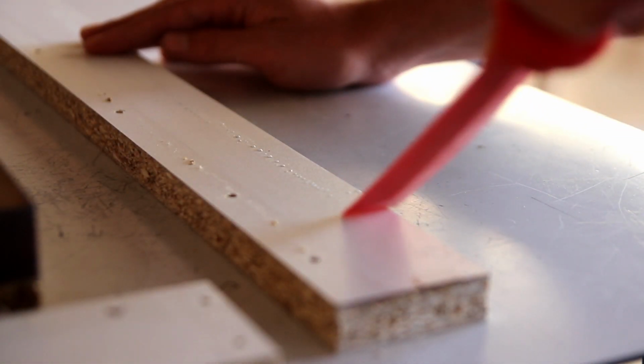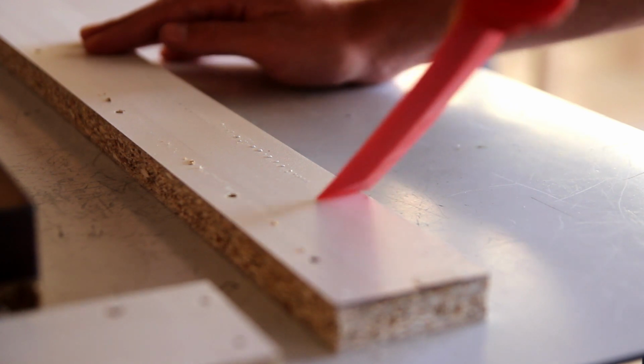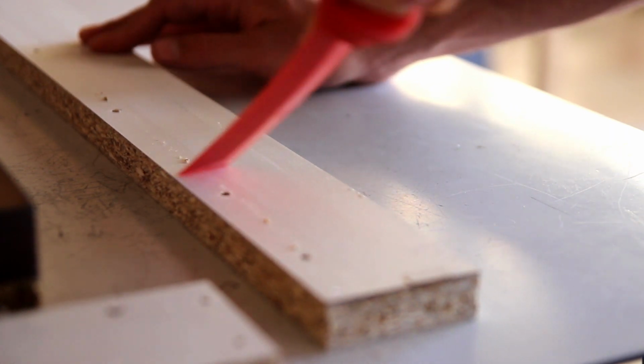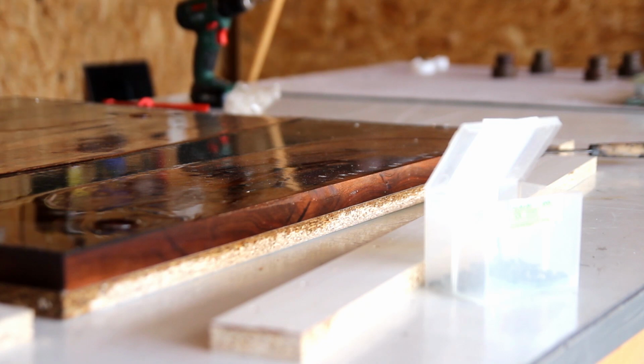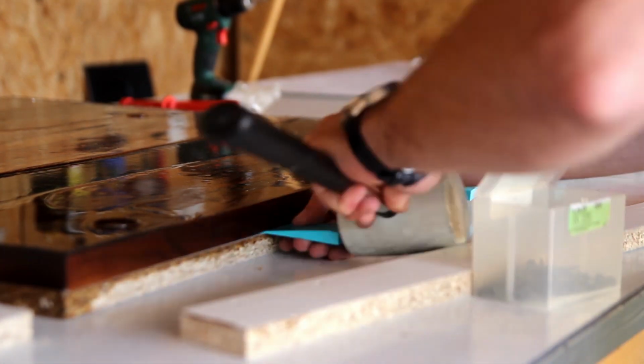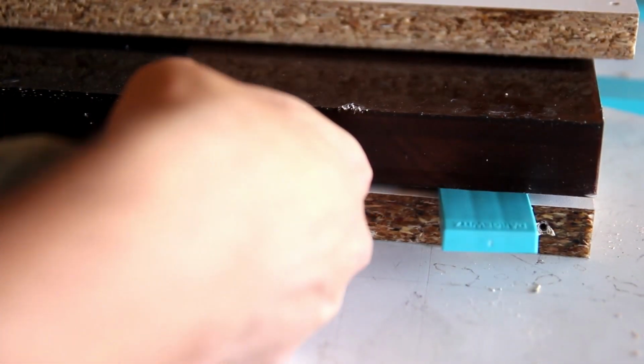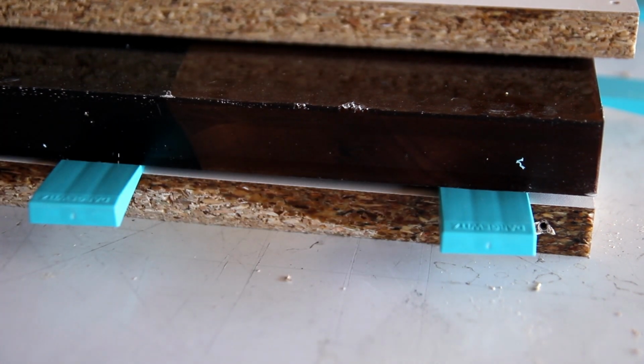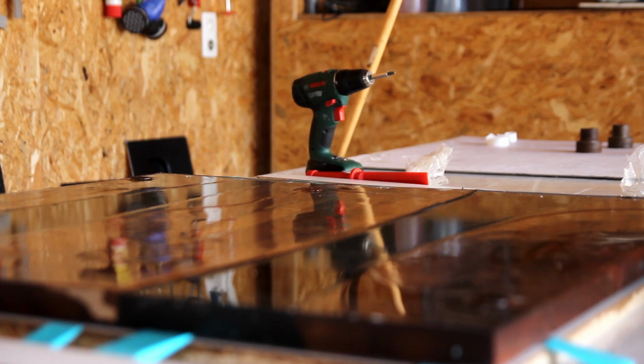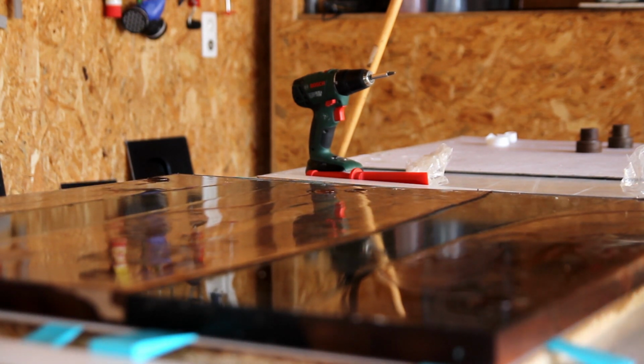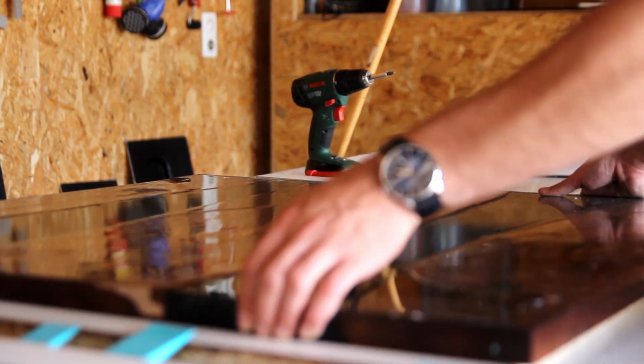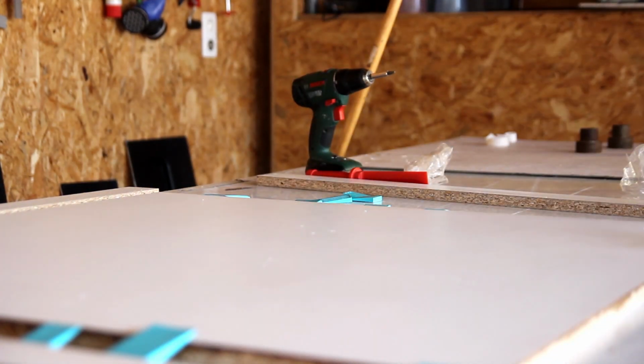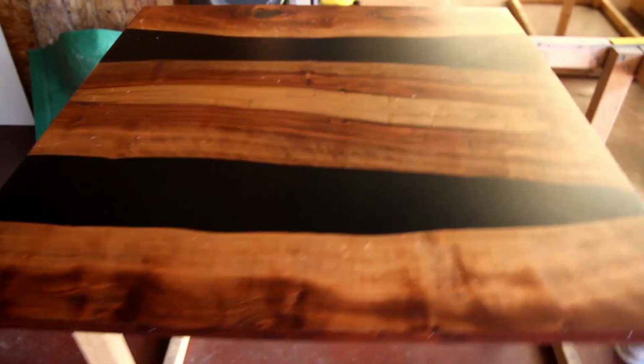What you could also have seen in the shots before is that I'm post-curing these parts in the sun. It went up to 60 degrees. Post-curing means that your epoxy resin will be stable up to these temperatures over time. For example, if you're casting your tables at 15 degrees during the winter and then put them outside at 30 degrees, there's a big chance that your epoxy might warp or cause some unpleasant surprises during the summer.